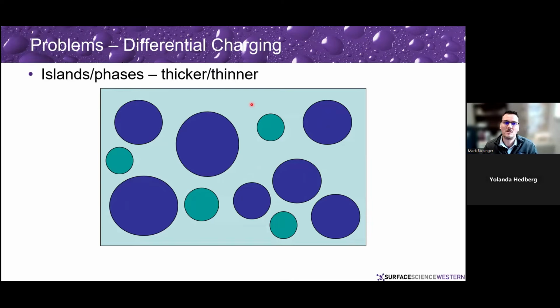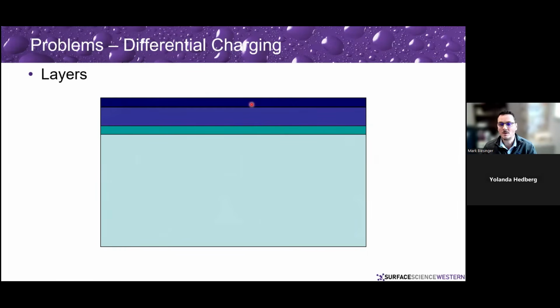So all these things are not behaving electrically the same, especially if that sample is attached, grounded to the holder of the system. And so the apparent positioning of all those things can change. And so you get split peaks and things based on the fact that things aren't behaving the same conductively, even though they're chemically the same. You can also see this in layers.